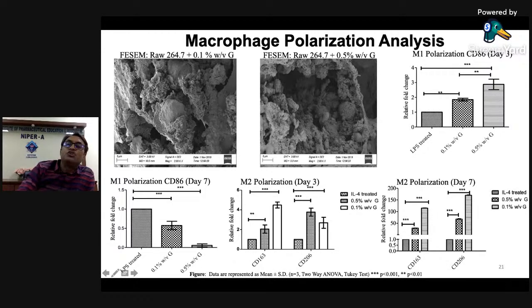So you see CD86 is increased in 0.5% on day 3, but surprisingly, if you grow the culture up to 7 days, CD86 decreases significantly, which means that M1, which is the pro-inflammatory macrophage, decreased after 7 days when grown onto the material.